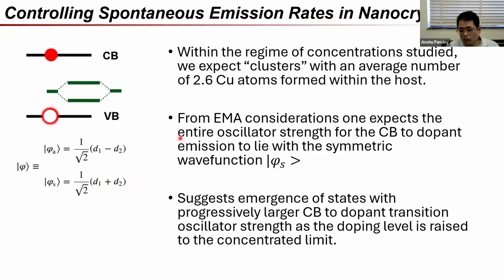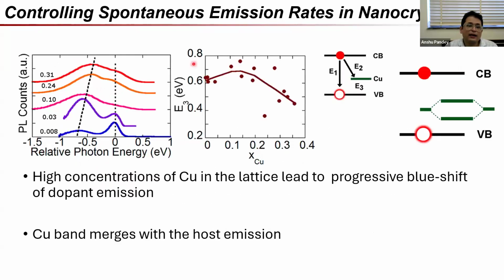And at the same time, what appears to happen is that the entire luminescence band, as the amount of copper increases in the system, seems to blue shift, gravitating towards the band edge of the material. So it's not to say that all of the copper atoms are increasing in energy higher up. It's not like that, but rather they are actually being pushed down towards the valence band.